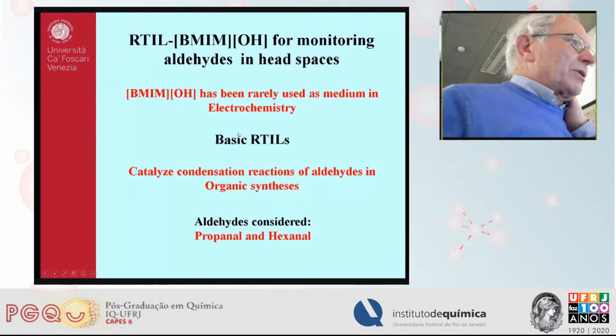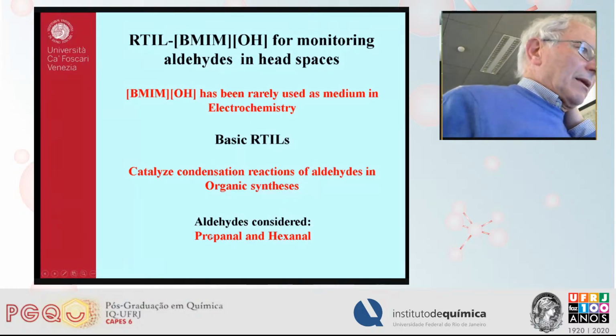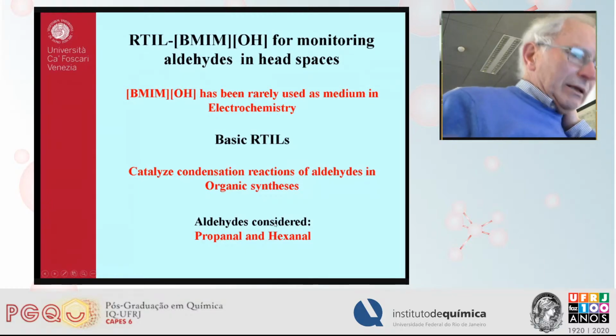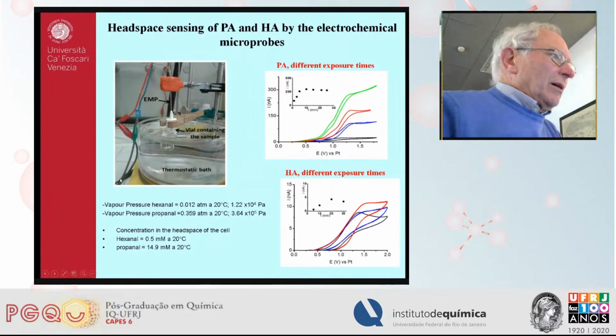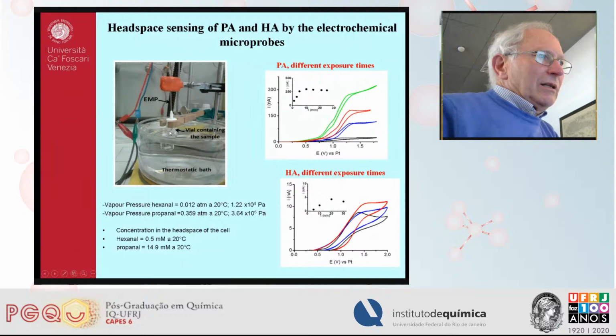So we explored the possibility of using this probe for two aldehydes, propanal and hexanal. Hexanal in particular is very useful for food analysis. So this is the apparatus we use. The probe is the same, this one, which was kept in the atmosphere of a vial, which was immersed in a water bath. This is in order to control the temperature, because the volatility of aldehyde strongly depends on temperature.